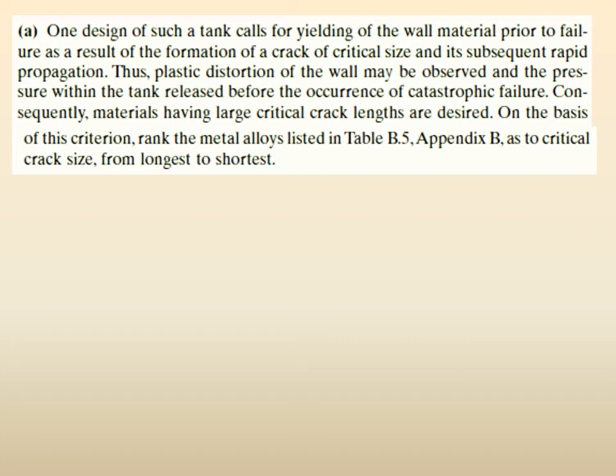First design approach is known as yield before fail. Yield before fail. When will it fail? It will fail as a result of the formation of a crack of critical size. There is a crack right now of some size 2A, suppose it is 1 millimeter. It will grow, it will grow, it will grow until it becomes, say, 10 millimeters. If the 10 millimeter is the critical crack size, then after that there will be rapid propagation of the crack and it will suddenly fail.